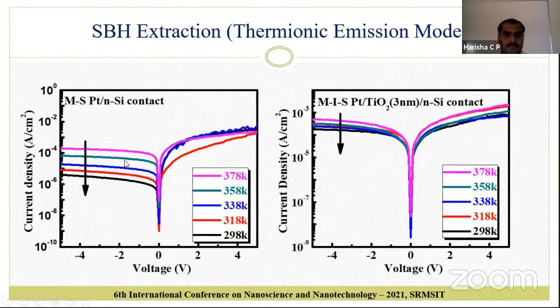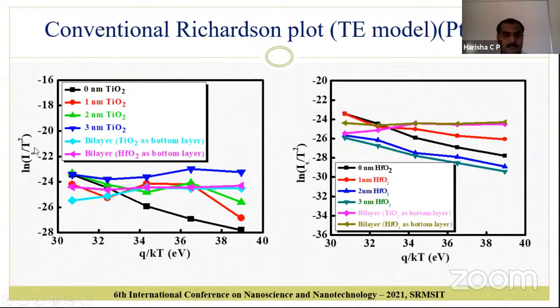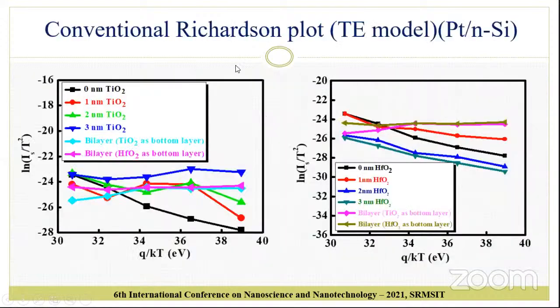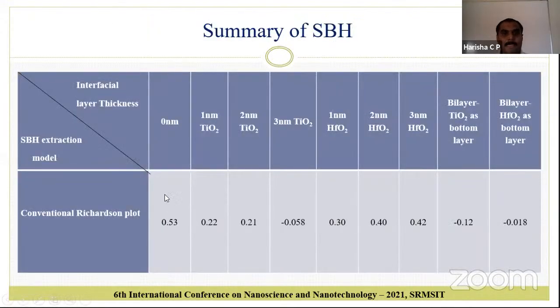So we have observed that the conventional Richardson plot, in the curve you can see here, gives a non-linear behavior, both in terms of MS contact as well as MIS contact structure. Here also, in terms of MS and MIS contact structure, we have observed a non-linear behavior. After the extraction of Schottky barrier height using this plot, we have observed that the Schottky barrier height for MS contact was 0.53 electron volt, and with the 3 nanometer TiO2, the Schottky barrier height was minus 0.058. This means the Schottky barrier height has been decreased to a negative value.